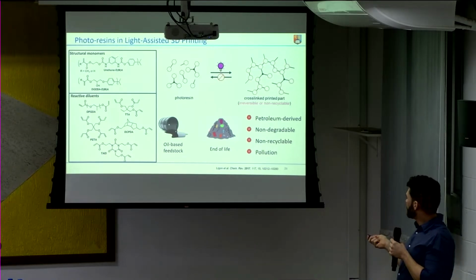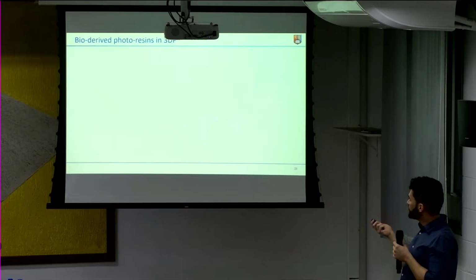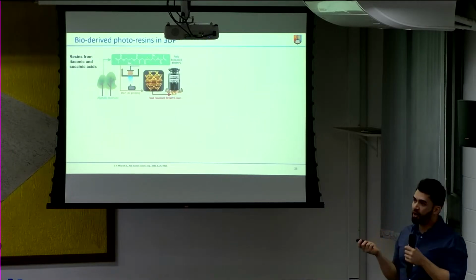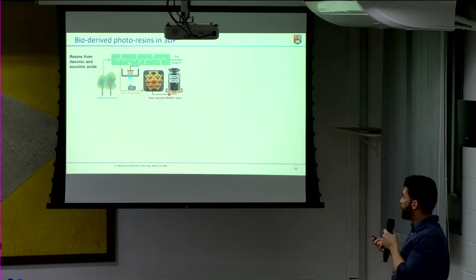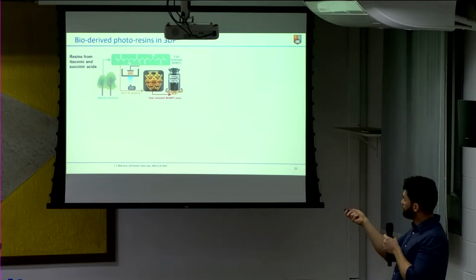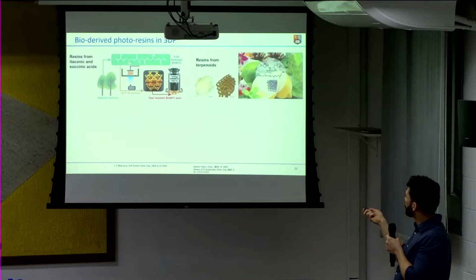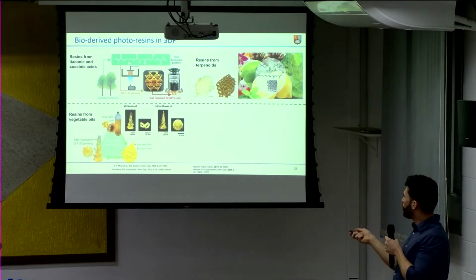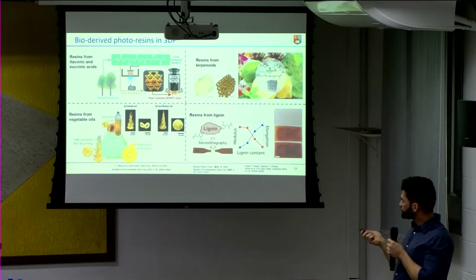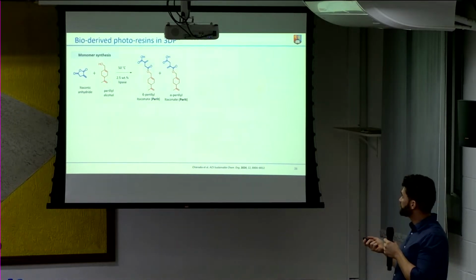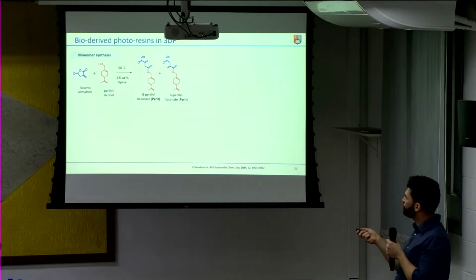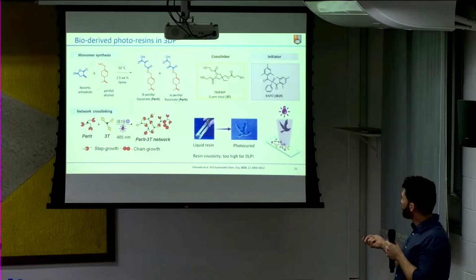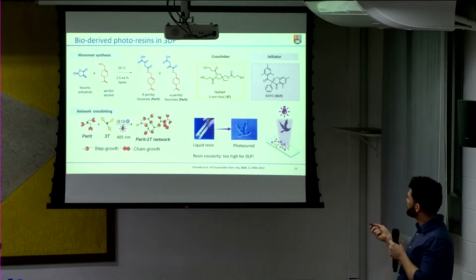So we need to fix that, but how do we do that? What researchers have been doing is trying to make resins based on bio-based compounds. So for example, itaconic and succinic acids, or terpenoids, vegetable oils, and lignin. We've done some work in that sense as well. So we made some monomers from itaconic anhydride and perillyl alcohol, which is a terpene, by esterification with an enzyme. And then we made a resin with a thiol crosslinker, BAPO as photoinitiator.